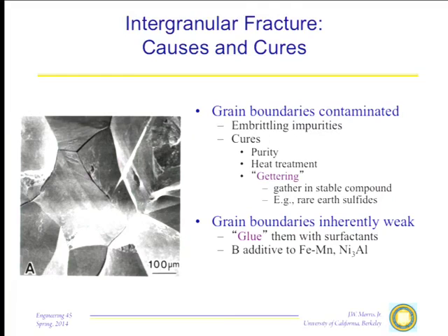There is an intermediate temperature called the embrittling temperature at which the impurities will go to the grain boundaries and cause this disastrous effect. So if you can simply heat treat the steel, or the aluminum alloy, so that you avoid this embrittling temperature, then you can be safe. That's a very iffy way to do things because the embrittling temperature is sensitive to a number of variables. It's rather hard to predict and control. So you can do that, but you're playing a somewhat dangerous game.